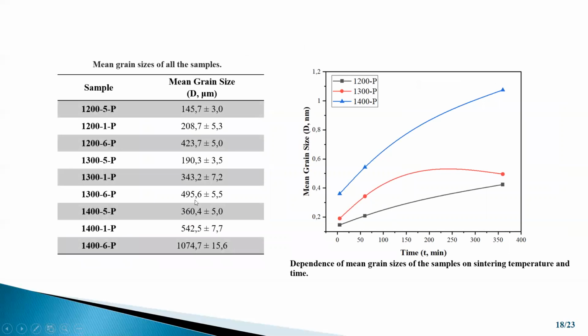The mean grain sizes of all samples are given in this table. It is seen that the highest grain size value was reached after 6 hours of sintering at 1400 degrees, and the lowest grain size value was achieved by sintering at 1200 degrees for 5 minutes. However, it can be said that the increase in grain size with time is not linear. This figure shows the dependence of mean grain sizes on the sintering temperature and time. As we can see, when the sintering time is increased from 5 minutes to 1 hour, the grain size of the samples increased almost 2 times. But when the time is increased to 6 hours, the increase in the grain size did not occur at the same rate. This situation shows that the grain growth is limited at a certain point.